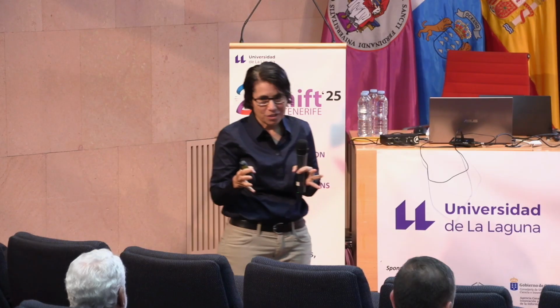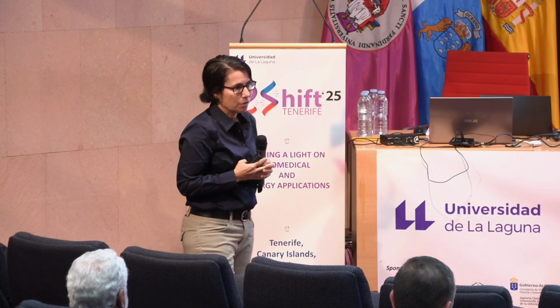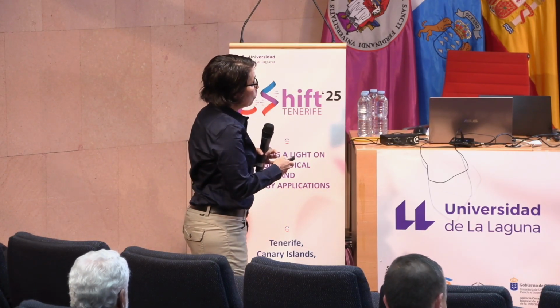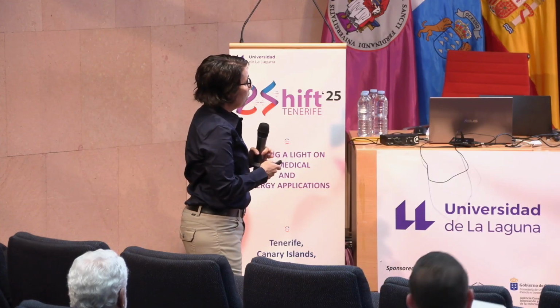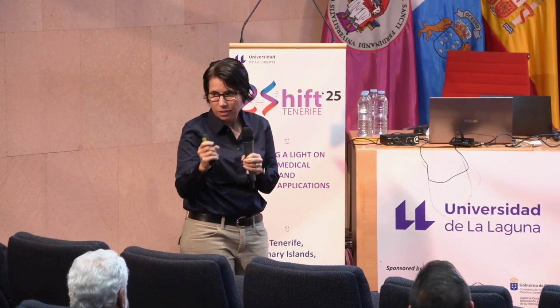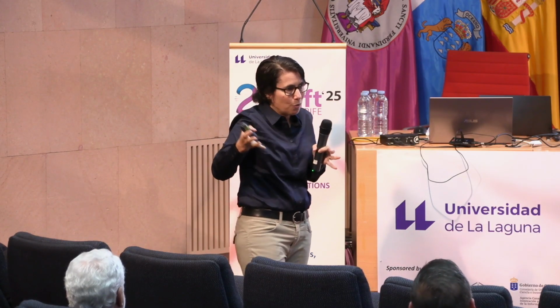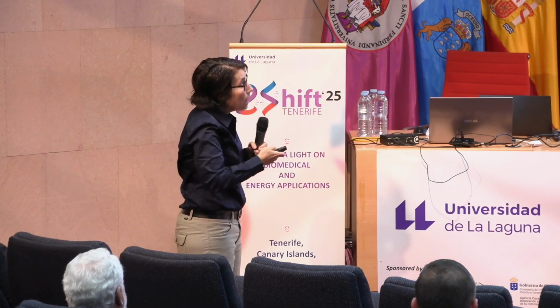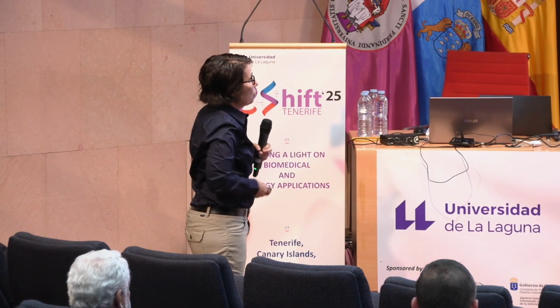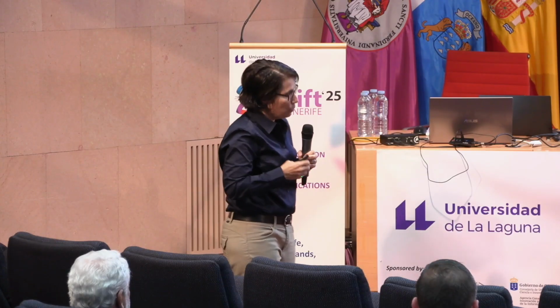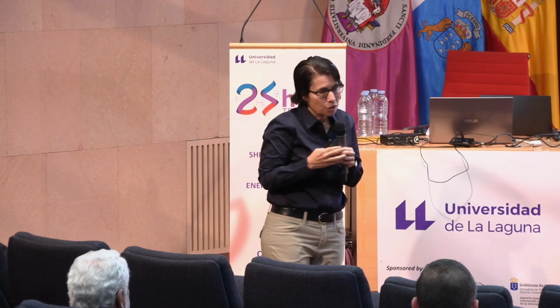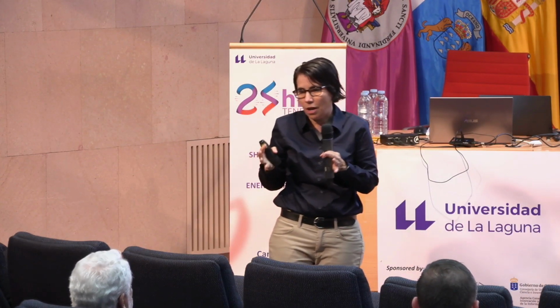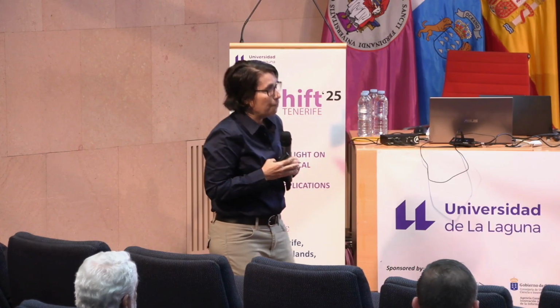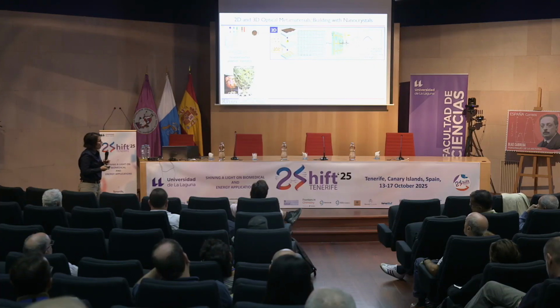If you didn't do the ligand exchange, it just looks like the individual nanocrystals. Each one of these rods gives a characteristic response. It looks like the dielectric function characteristic of gold, but it depends on the geometry that we print. In the early days, we were interested in this idea: could you build large area optical metamaterials? These processes were commensurate with those ideas.